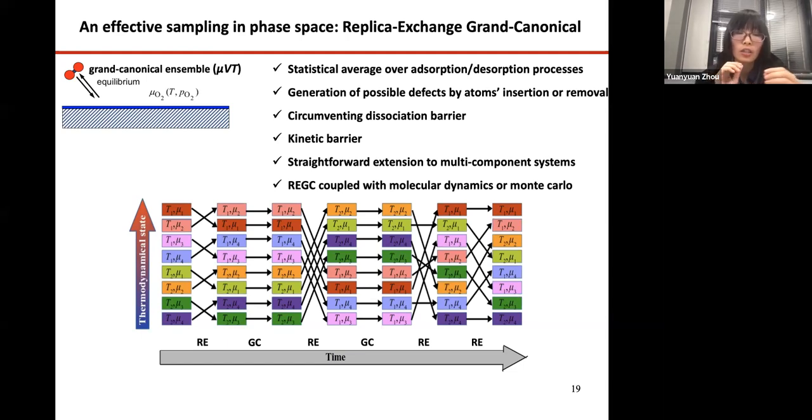After each replica swap or particle exchange attempt, ab initio molecular dynamics follows to further relax or diffuse the configurations. By combining these two methods, the sampling is improved by allowing replicas at relatively low temperatures to reach high temperature regions where the system can overcome the kinetic barrier easily.